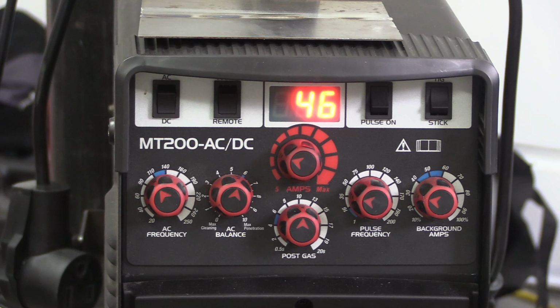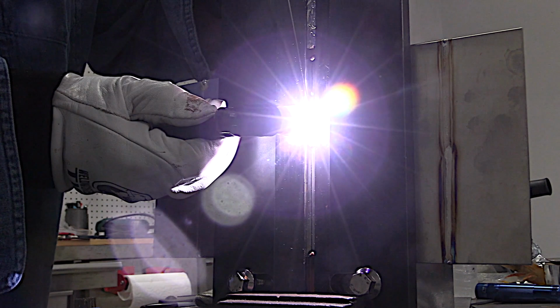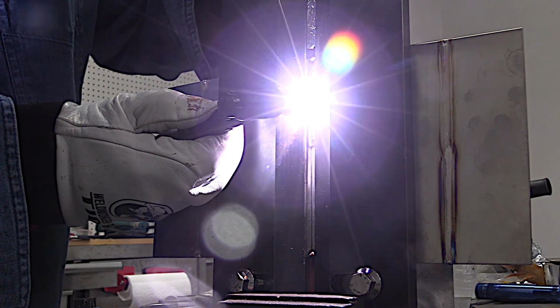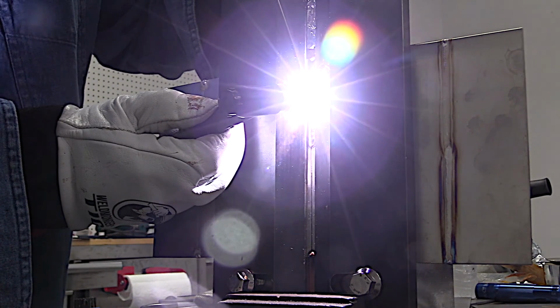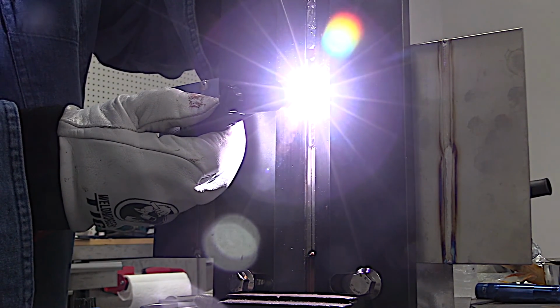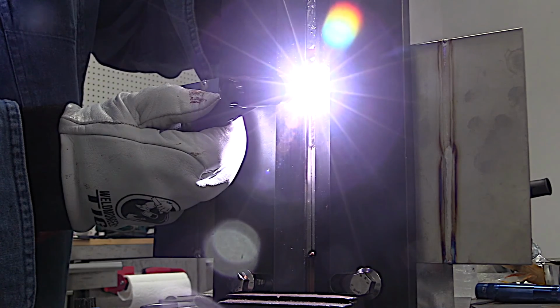Notice that I'm reading out 46 amps here and I'm welding .063 material. I've found that with stainless you need about 2/3 of an amp per thousandth of thickness for a butt joint like this, especially if you have any gap at all. That 1 amp per thousandth rule is a guideline. It works on carbon steel and some other alloys, but a little bit less for stainless, a little bit more for aluminum.